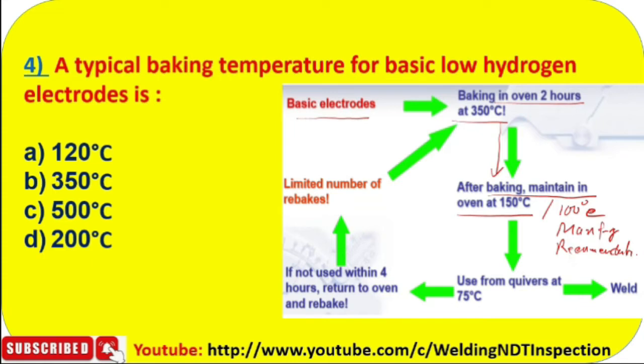First you bake in the oven at 350 degrees centigrade for 2 hours. After baking, maintain it in a quiver, at 150 degrees centigrade. Then it is taken from the quiver to weld. After taking it from the quiver, you open the quiver and weld. If some parts are not used within 4 hours, return them to the oven and rebake. So this is the process. You understand the process.